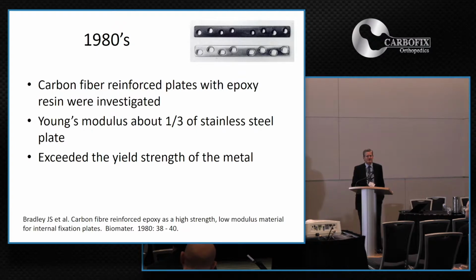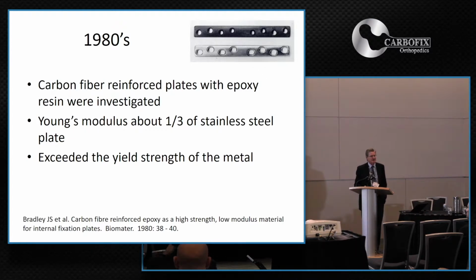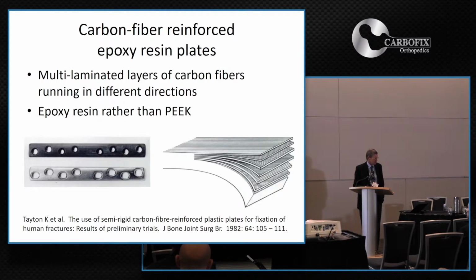If we go back into the literature in the 1980s, carbon fiber reinforced plates were first being studied. And this was done with epoxy resin rather than with PEEK. The difference was that the Young's modulus was about a third that of stainless steel plates, and they exceeded the yield strength of the stainless steel plates. And so they used these multi-laminated carbon fibers and then epoxy rather than PEEK.